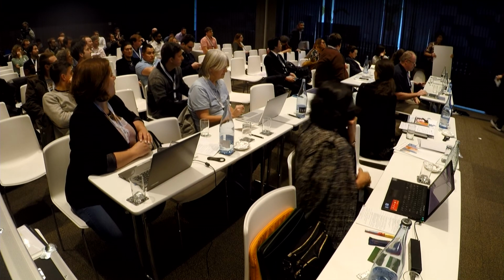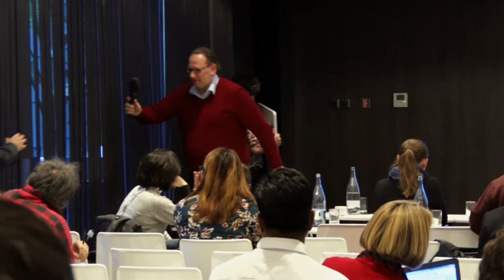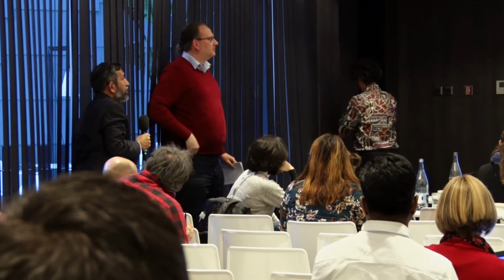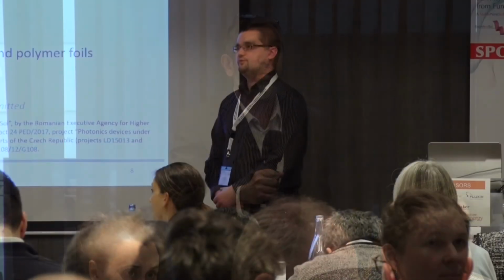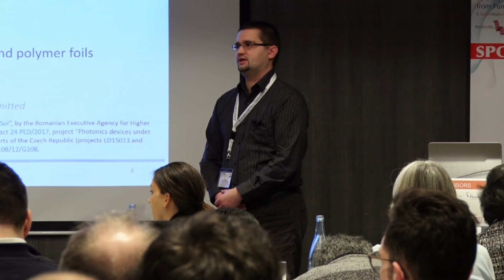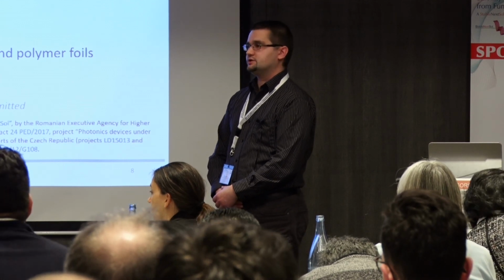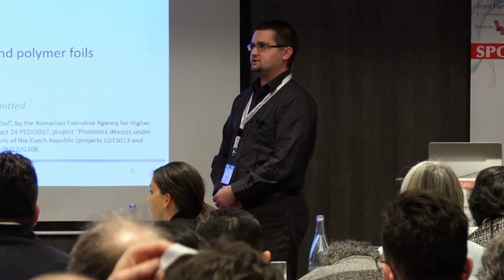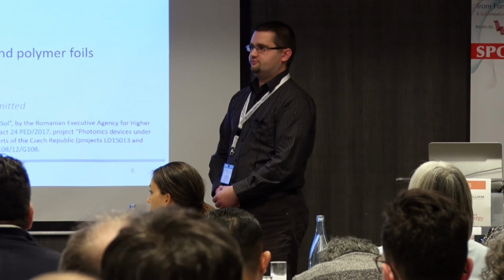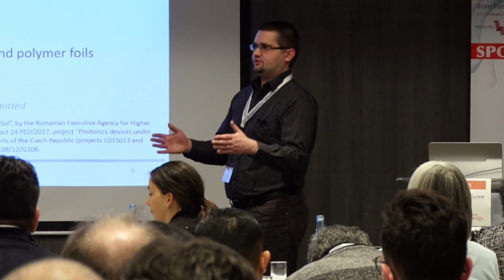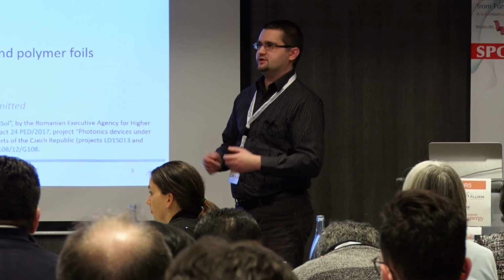Thank you. This irradiation on ITO, was it the ITO side or the polymer side that was facing the proton beam? We tried both. And in both cases it was? In both cases it works as a protection, quite surprisingly. But obviously if you could coat the sample from both sides, it would be the best.